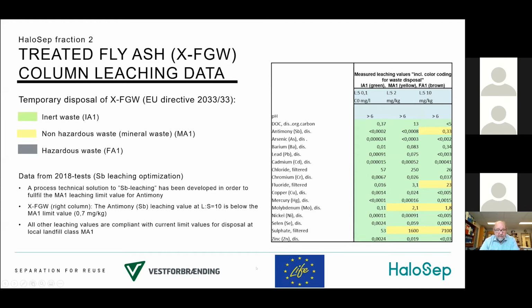A little more about challenges during the development of the process. During the pilot testing, we experienced that antimony leaching was occasionally above 0.7 milligrams per kilo, which meant that we had to go to a hazardous waste disposal site. But in 2018, we found a technical solution for the antimony leaching, in order to fulfill the mineral waste leaching limit for antimony. Next slide, please.